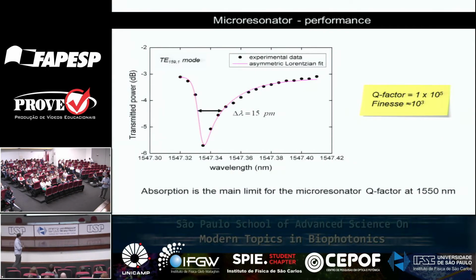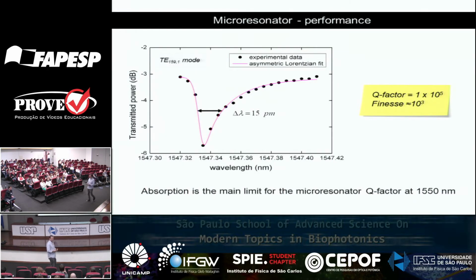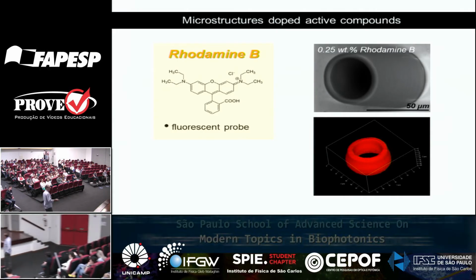If you are wondering about the Q factor, the quality factor of our resonators is on the order of 10 to the 5th, which, of course, is maybe 10 times smaller than what you can get with regular silicon photonics. But in here, we have a polymer. And, of course, polymer does have absorption in the near infrared, right? So here, that's the state of the art. If you do a polymeric thing, you're not going to be able to get anything smaller than this. But it's competitive with whatever you have in the literature, more or less. Of course, you can dope, as I mentioned before.